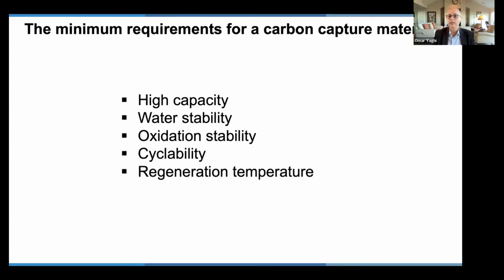You also need your regeneration temperature to not be very high, because that's your energy input, and that's basically the binding energy of CO2 into the pores. So you don't want that to be so strong that you have to heat the material up to hundreds of degrees to remove the CO2. All of these are extremely challenging, but you can see from my earlier description of MOFs that we've been working for the last 25 years to make materials that meet these requirements.